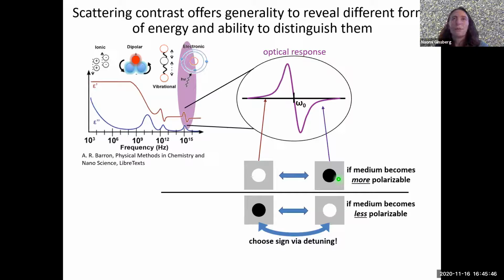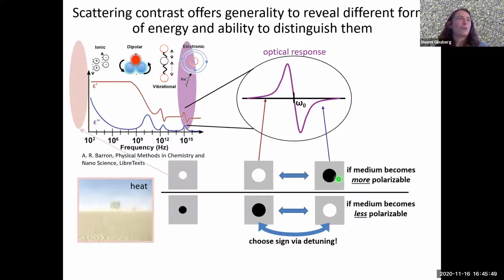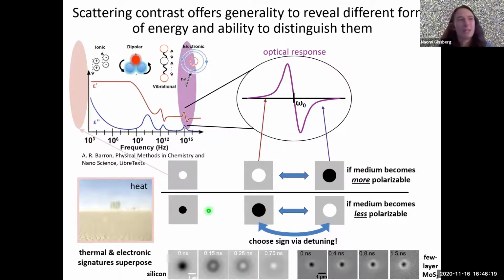Now, where might that be useful? Well, it's definitely useful if you're interested to know about heat in your sample as well. And here I'm thinking about heat in the context of, say, a lattice expansion or contraction. So this is really a DC contribution. So that can, in principle, have two different signs as well. But we can always select the sign of the electronic quasi-particles to be opposite of what we measure for heat to look like. And that's something that we've done in both directions here, for example, with silicon, and then also in this few layer molybdenum disulfide that I'll talk about shortly.